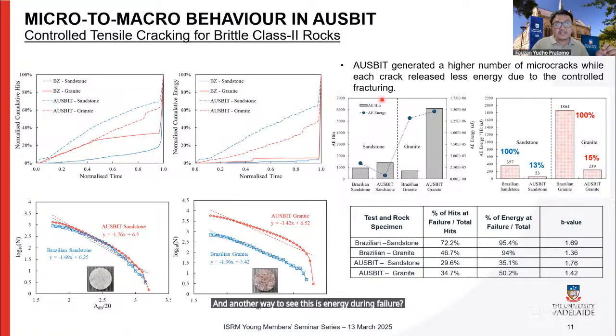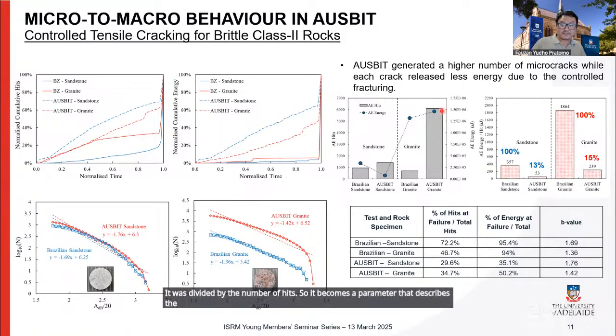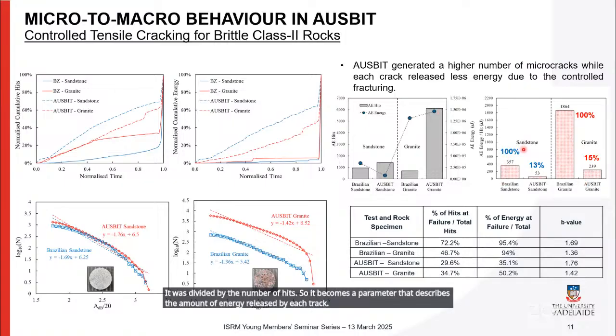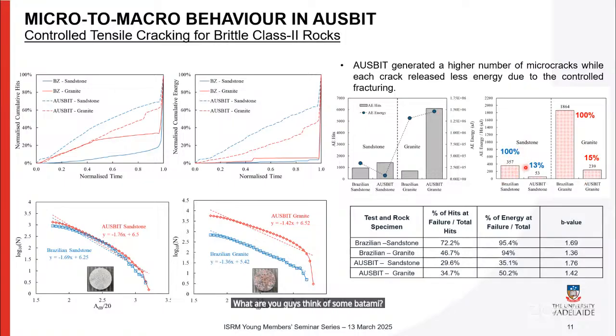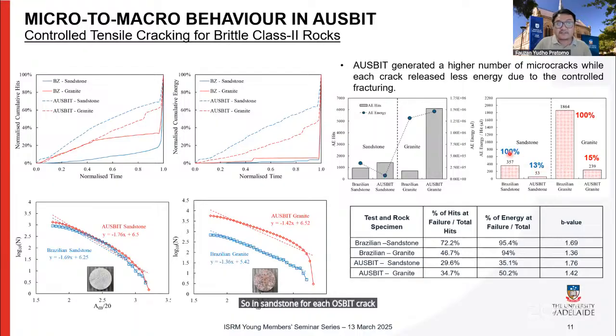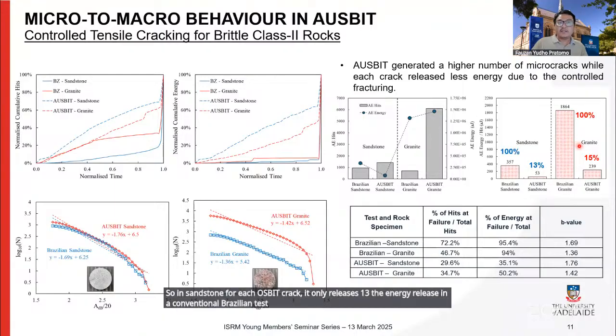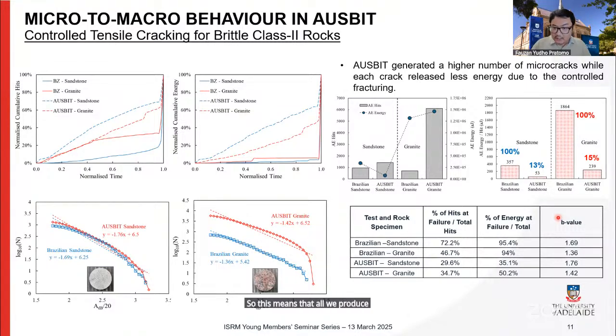Another way to see this is the energy during failure divided by the number of hits. So it becomes a parameter that describes the amount of energy released by each crack. In sandstone, each AUSBIT crack only releases 13% of the energy released in a conventional Brazilian test. And for granite, it's only 15%, while in the conventional Brazilian test, it releases a significant amount of energy. So this means that AUSBIT produced a higher number of micro cracks, while each crack released less energy due to the controlled fracturing.